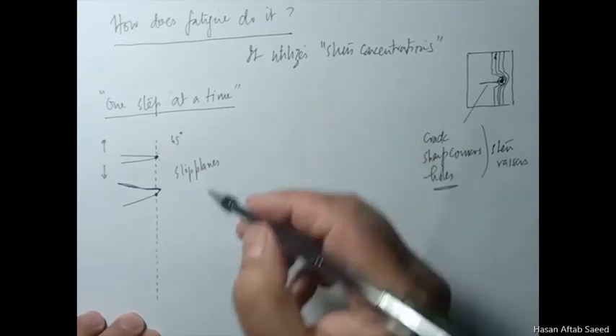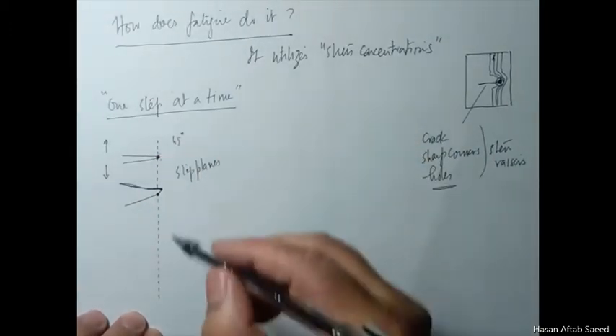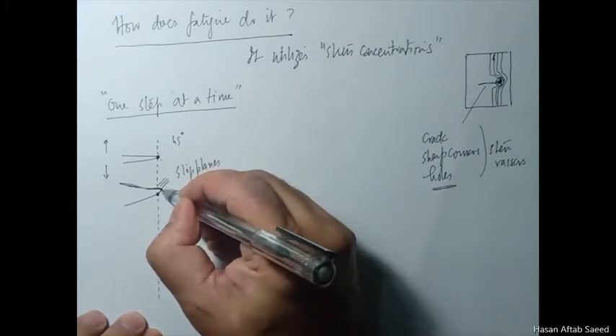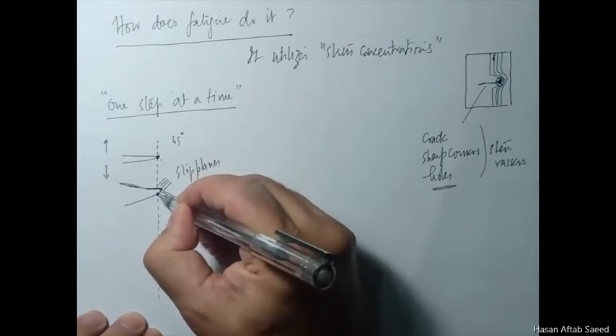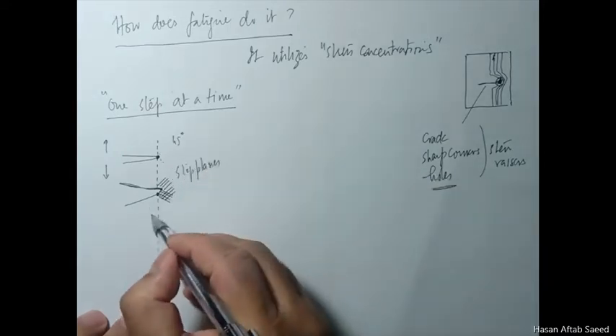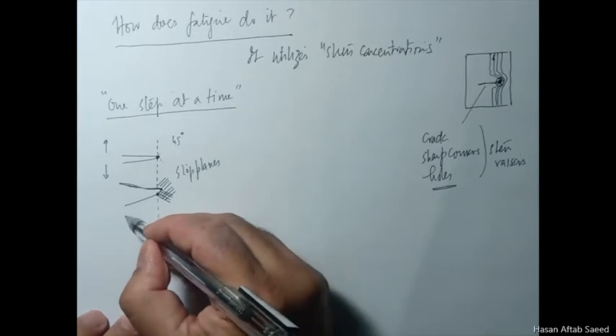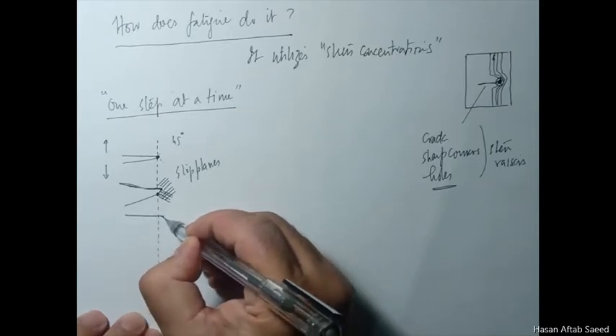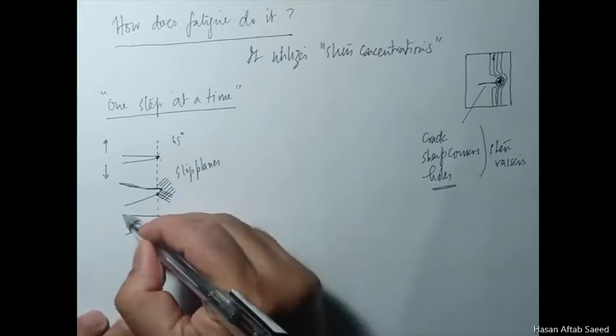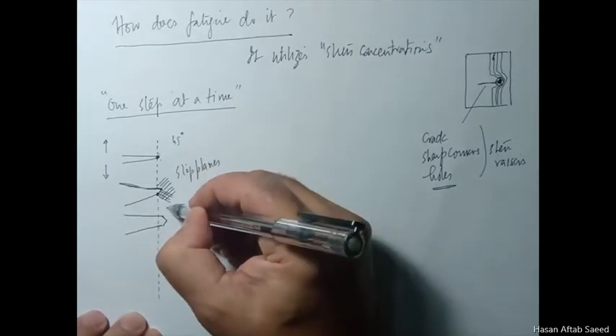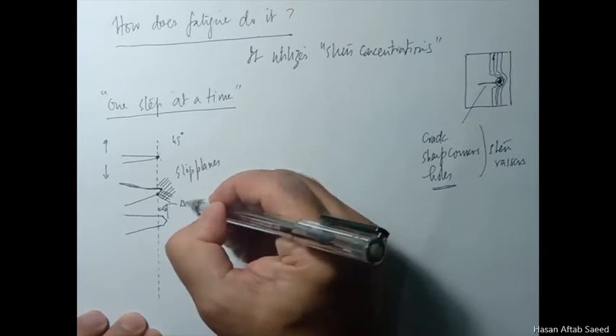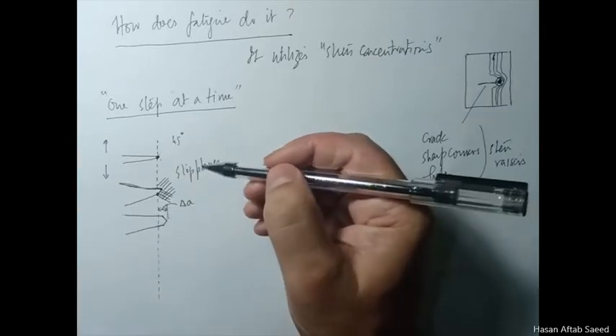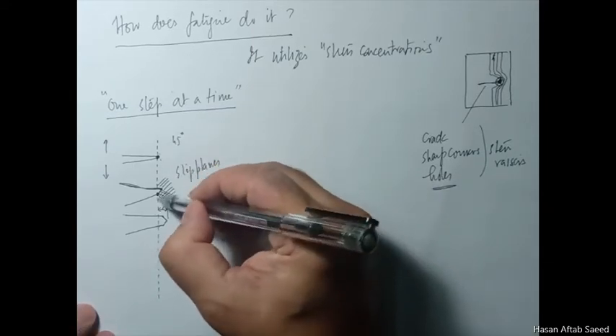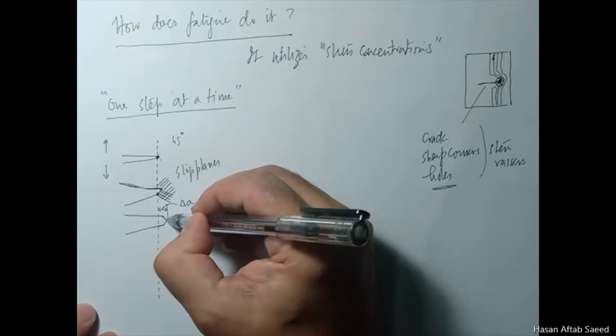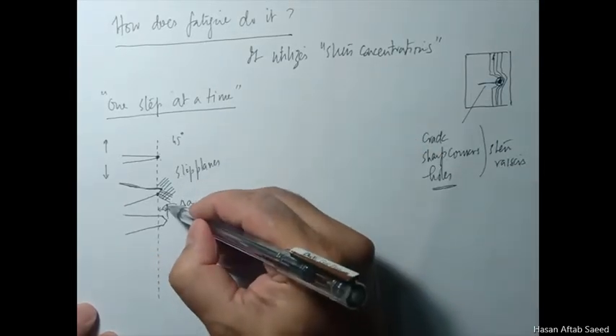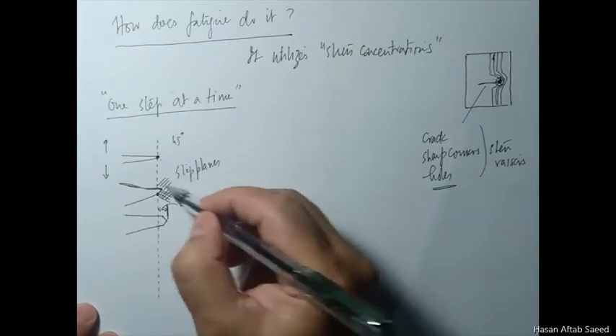Something like this happens. Now, slip planes: there's not just one slip plane, there are complementary slip planes, and many slip planes are here. So what happens is ultimately you get this. So you have an extension of crack by an amount delta A. This was the original point of the crack, and here it has extended by delta A as a result of all these slips.